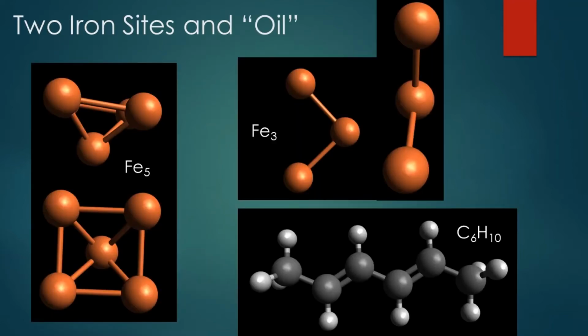I began by creating some test molecules and optimizing their geometries in Avogadro, a molecular modeling software. Since the total additives in cast iron are less than 5% by mass, they were neglected for a pure iron structure. Iron takes on a body-centered cubic structure, and I wanted to investigate two possible adherence sites, on the top of the cube, which I call iron 5, and along the edge, iron 3. The molecule chosen as a model drying oil is C6H10. It's assumed the interactions between the oil molecule and the iron surface are local, so I only needed to investigate what happened immediately at the site.